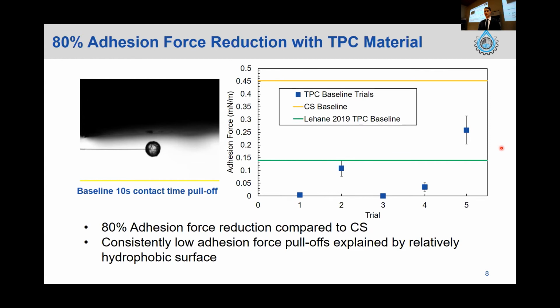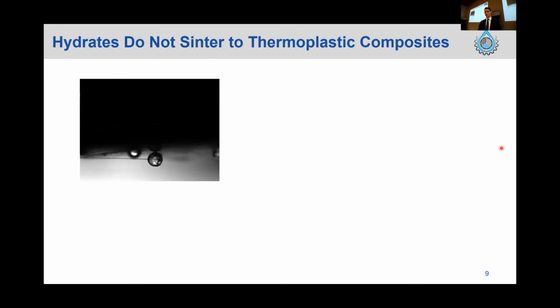So after this baseline, the next direction of the research was to investigate how this adhesion might vary if the contact time was increased. So for these baseline measurements, there was only a 10-second contact time, which is comparable to other studies that have been done on other materials. And so this is just a short video of the pull-off for a 1-hour contact time. So this had been brought into contact for an hour, and then pull-off was performed.